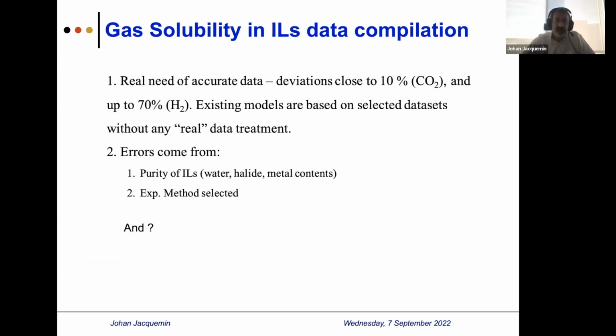So, of course, looking at the data that I have in the database, and which reflect some of the SDS volume 103 conclusion, no data set could be recommended, even for the IUPAC sample. And deviation close to 10% for CO2 are quite often reported for all ionic liquids that I have. And deviation with statistical analysis of up to 70% for hydrogen. And basically, people develop models, kind of predictive models using data. However, how is it possible to do so without any recommended data set? That's a good question. So probably prior to move to simulation, probably we need to get really good data.